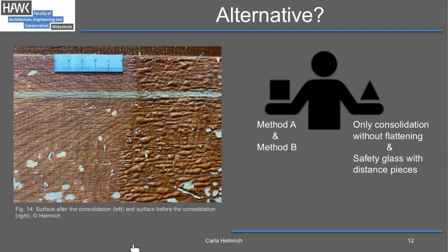When noticing this, I of course was thinking of an alternative method, but had still the reuse of the door in mind. So a possible alternative to laying down the blisters could be maybe the following. The large blisters are left in place and only consolidated on their surface as well as from the inside. However, the significantly elevated level of the blisters would still remain and be extremely vulnerable to punctures or mechanical stress.